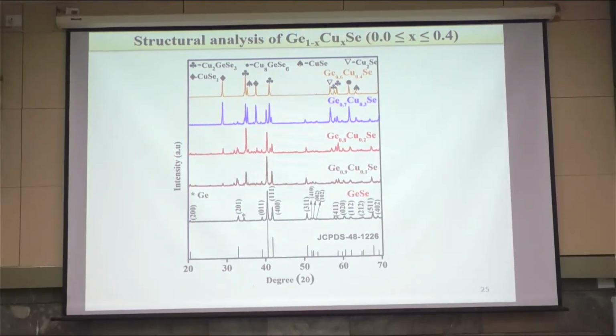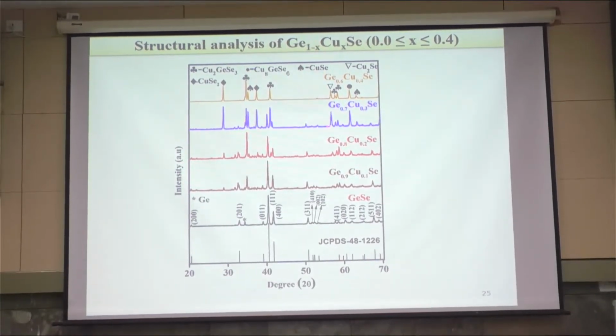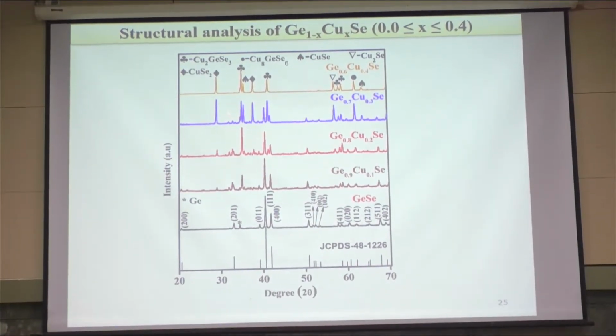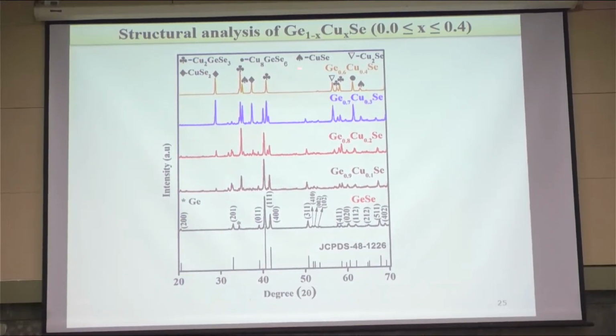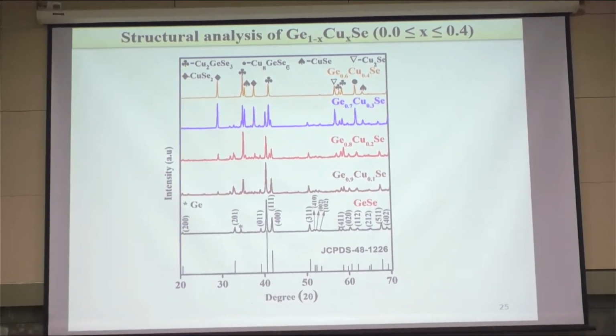And these are the structural features, but here the system behaves quite differently. That means the secondary phases are quite dominant, and copper-rich secondary phases were observed, compared to the tellurium substitution at the selenium site, because the tellurium substitution is quite favorable, and the solid solubility of tellurium in germanium selenide is quite high. But when we substitute the copper into the germanium selenide, secondary phases were formed, especially copper-rich secondary phases. So the system contains a lot of mixed phases, and of course the grains are highly interconnected, and we have a highly compact structure of this copper substituted germanium selenide.